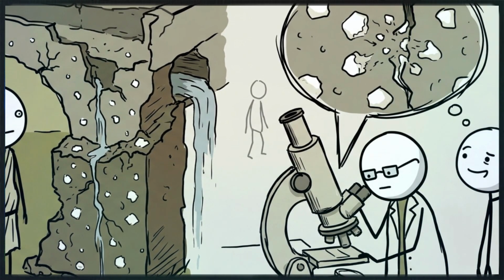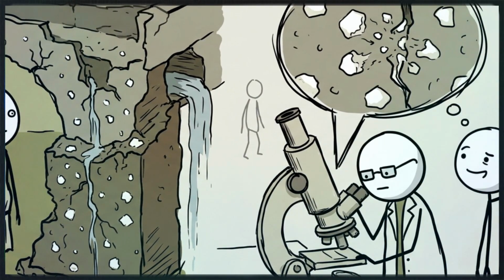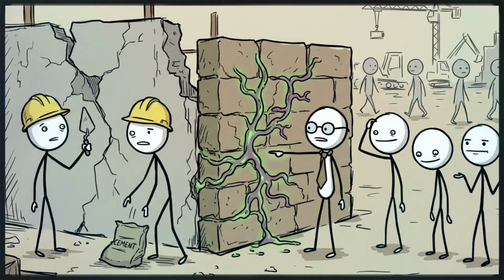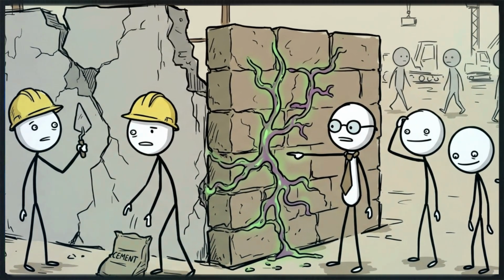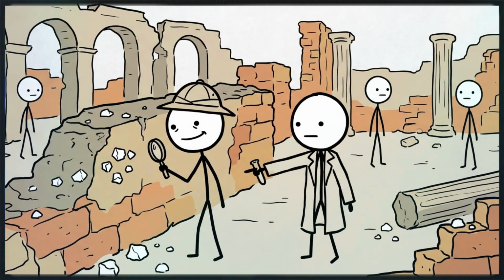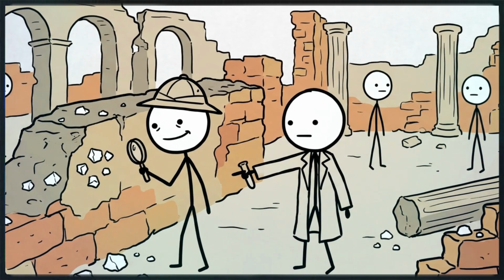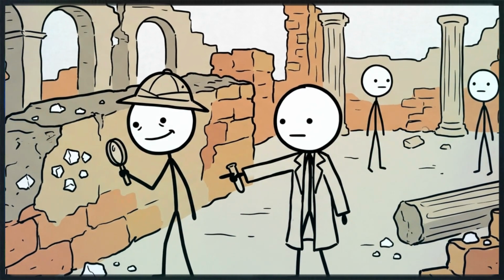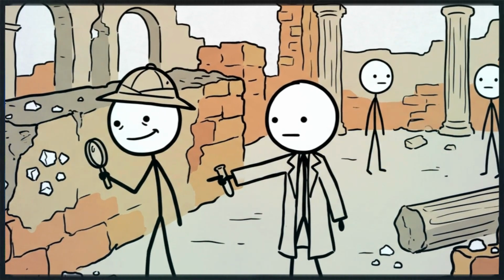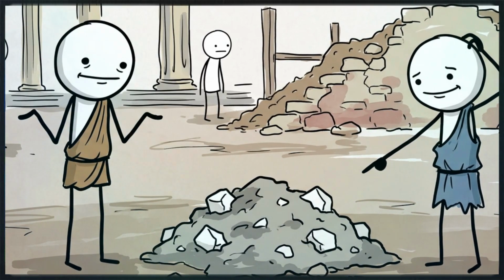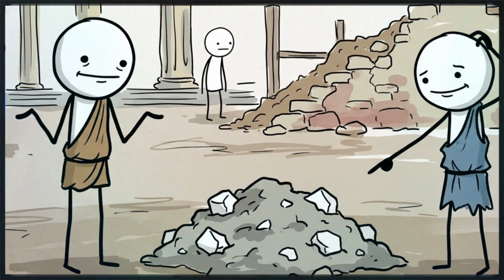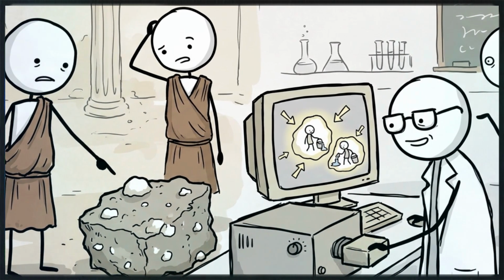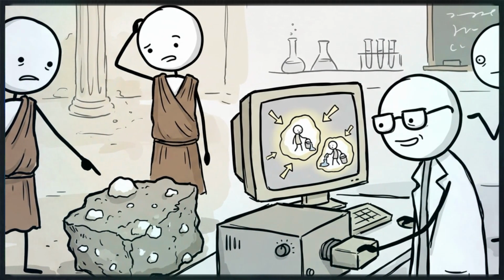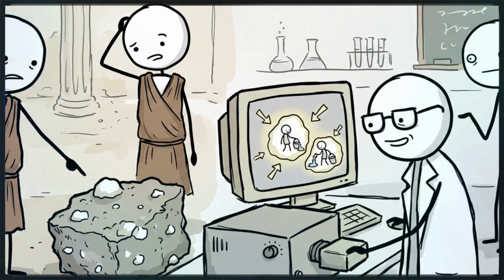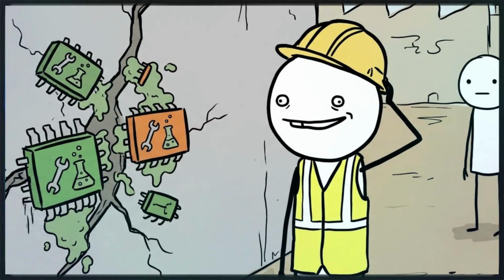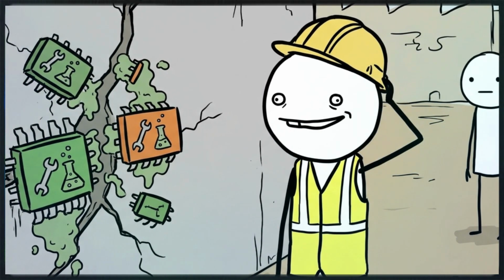However, the true scientific shockwave regarding Roman concrete was only recently unlocked by modern microscopes, revealing a brilliant, autonomous, self-healing mechanism that completely defies modern construction paradigms. For decades, archaeologists and material scientists noticed small, bright white millimeter-scale chunks of calcium scattered throughout ancient Roman ruins. For generations, these lime clasts were dismissed as evidence of sloppy mixing or poor quality raw materials. In reality, modern spectroscopic imaging has revealed that these lime clasts were deliberate, highly engineered micro-reservoirs of reactive calcium. They function essentially as embedded chemical microchips, programmed to repair structural damage.